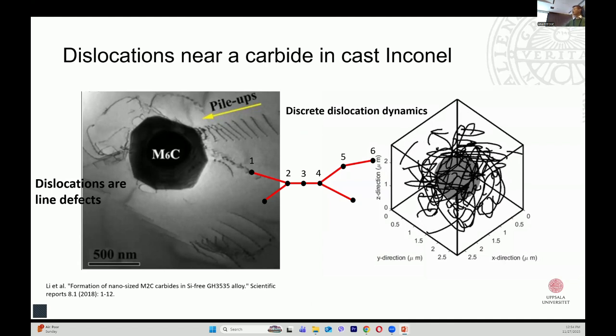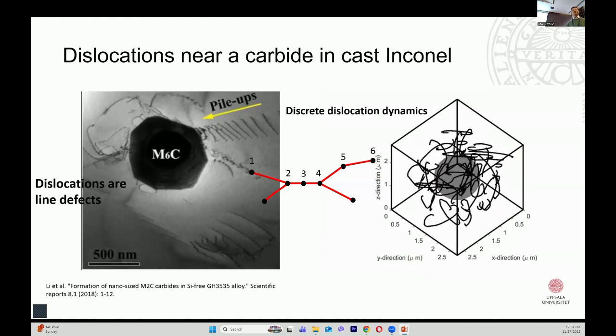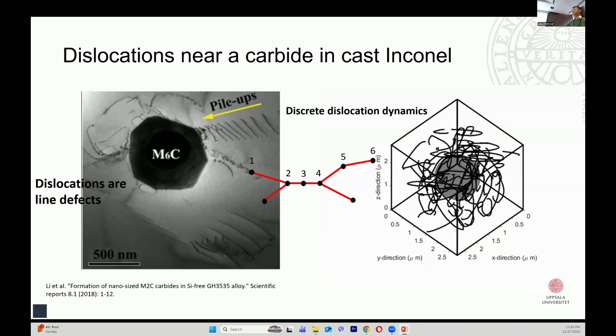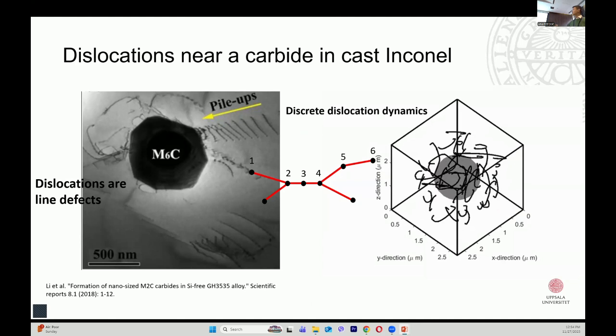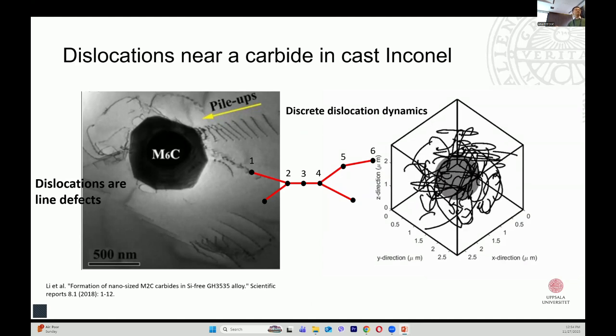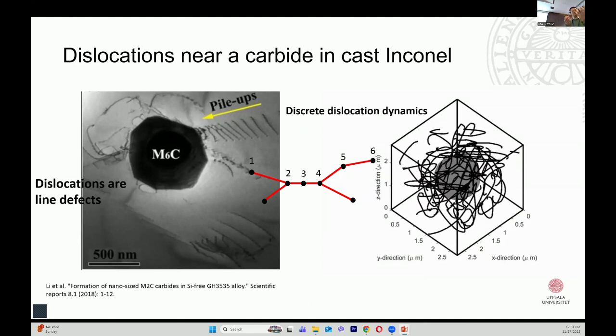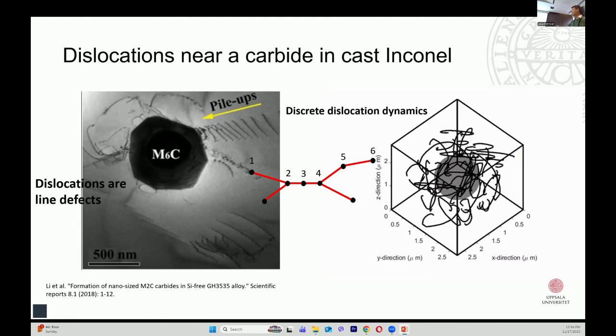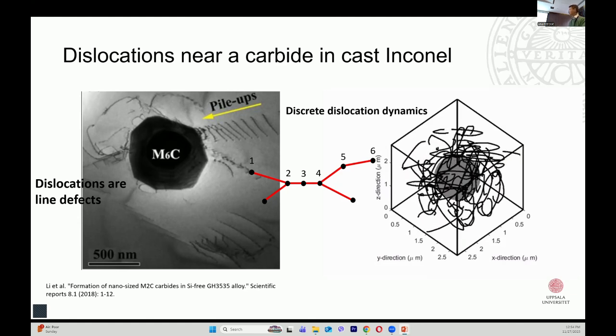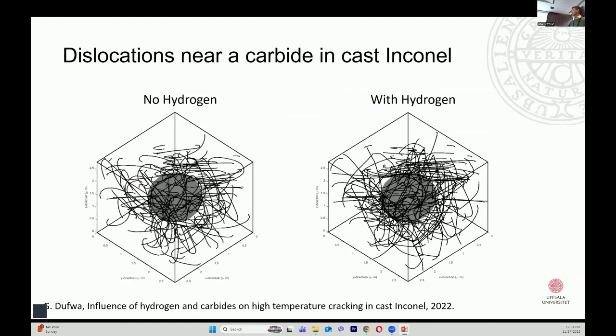So we tried to add an inclusion or precipitate into the pure metal, and we were able to simulate the dislocation entanglement with the approach around the precipitate, like this. And again, we simulated the scenario without and with hydrogen, and we get these two entanglements. What you can tell is with hydrogen, the entanglement density and also the complexity are increased a bit.